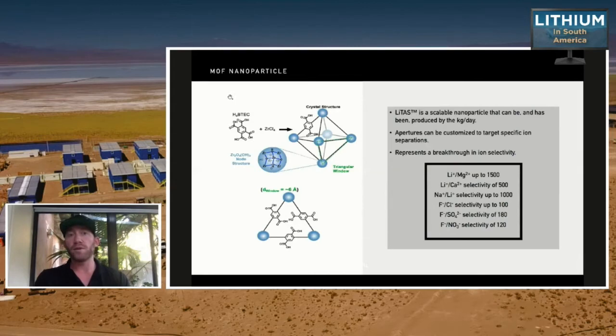A quick breakdown of what the nanoparticles are in the metal organic frameworks that go into the mixed matrix membrane. Basically, this was the original science that came out of Australia and Texas that showed these separations with single channel metal organic frameworks. So you have lithium magnesium separating at 1,500-to-1. You have lithium over calcium at 500-to-1. Lithium sodium at 1,000, and then you have these other separations that aren't really relevant to our lithium separation, but this was kind of the fundamental research. These nanoparticles have been produced by the kilogram a day, so it's readily available when we reach the piloting stage. The apertures in the metal organic frameworks can be customized. So that's the next generation that we're working on, putting this MOF, a different type of MOF, into the mixed matrix membrane format.